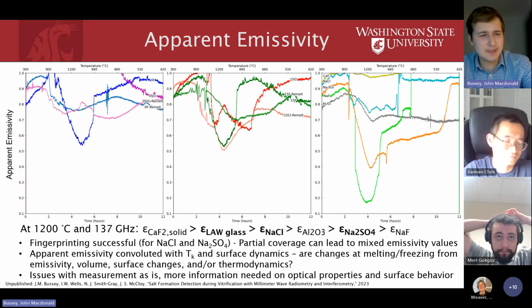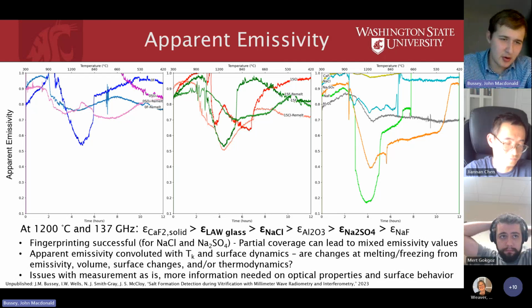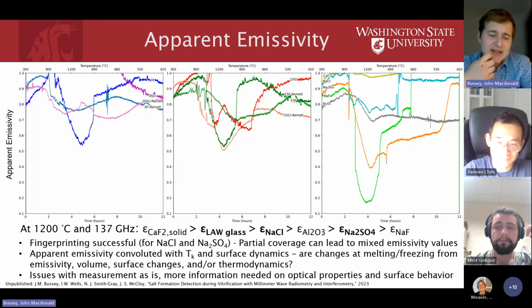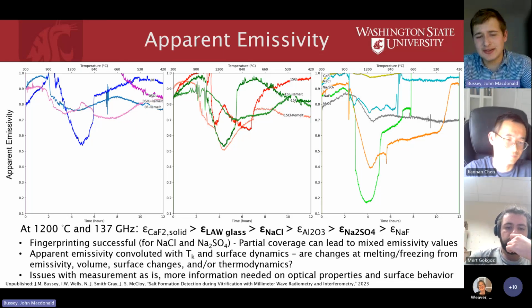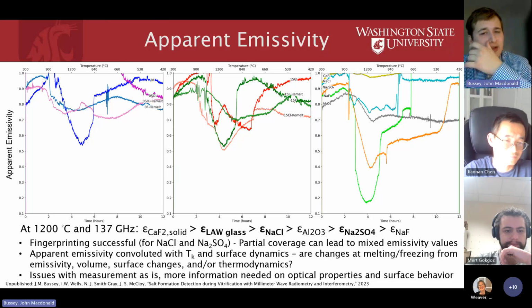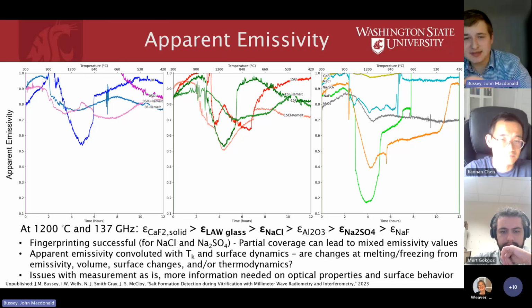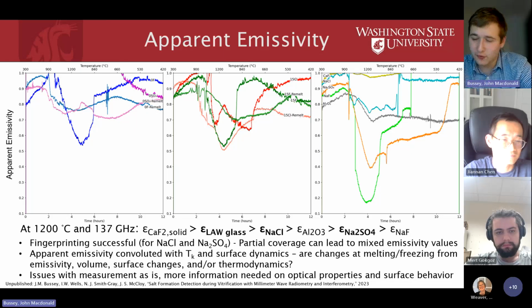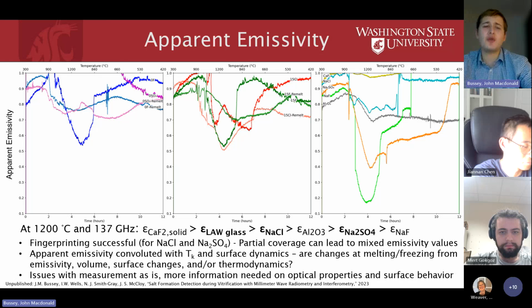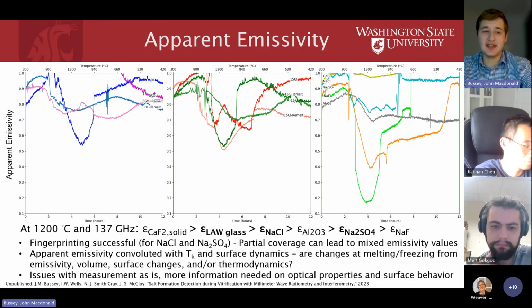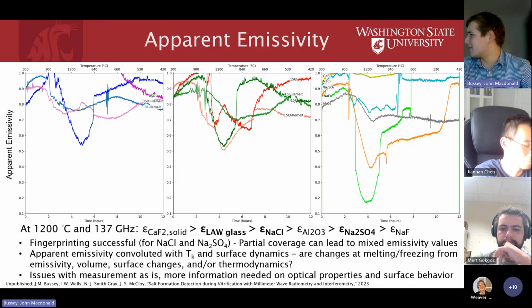And this behaved mostly as expected. Again, as temperature goes up, at least in the lower regimes, emissivity goes up. And at these wavelengths and at temperature, we're able to assign a range of what the emissivities look like. And with that, not only with seeing where it freezes, but also seeing the magnitude of the apparent emissivity, we can probably assign when salt is forming and what the salt is that is forming. We also notice that when you don't have full coverage of the surface, the emissivity that we detect is somewhere in the middle, and that again makes some sense because it's a surface measurement.